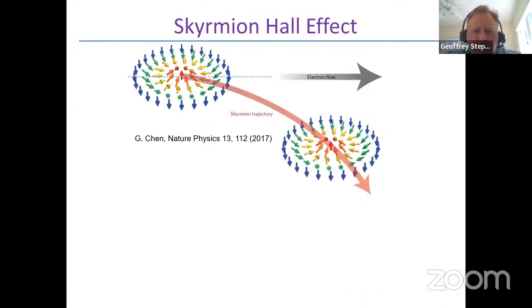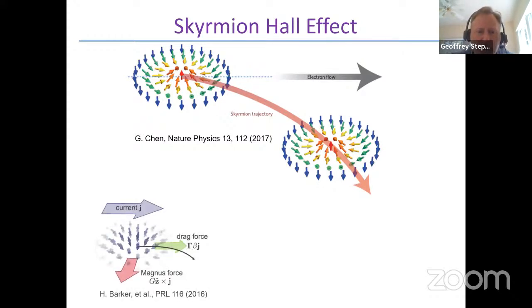So looking at the dynamics of these kinds of structures, stray fields or really uncompensated sublattices lead to other dynamics that are undesirable for devices, namely a skyrmion Hall effect. And the skyrmion Hall effect is just a phenomenon that happens when one tries to drive in a linear trajectory something that has a gyrotropic nature to it. So think a spinning baseball, or think a magnetic skyrmion.